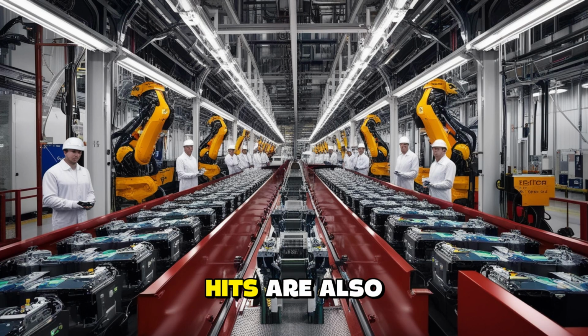Everyday bumps and hits are also part of the plan. The strong tray shell spreads the impact of debris or curbs and reduces local strain by over half compared to flat trays. In underbody impact tests at 35 km/h, the inside temperature rose less than 12 degrees C and recovered automatically after isolation. That turns damage into maintenance, not news headlines, the kind of safety that truly matters daily.